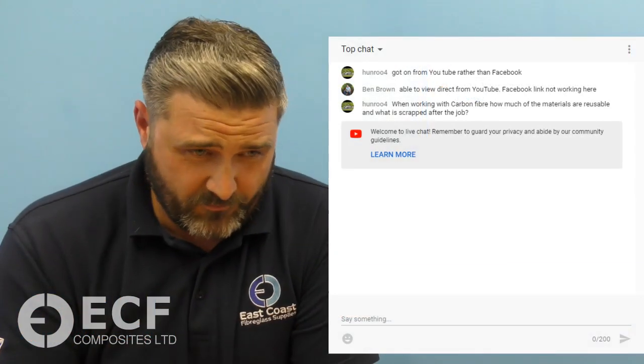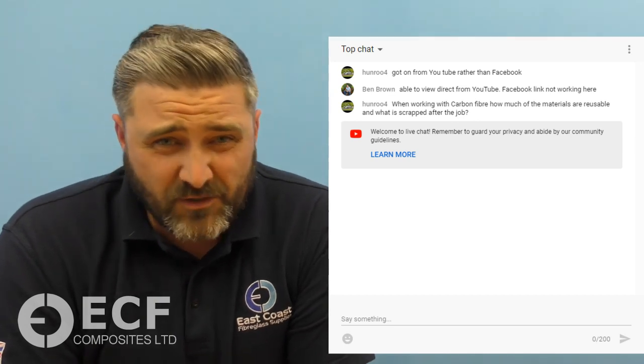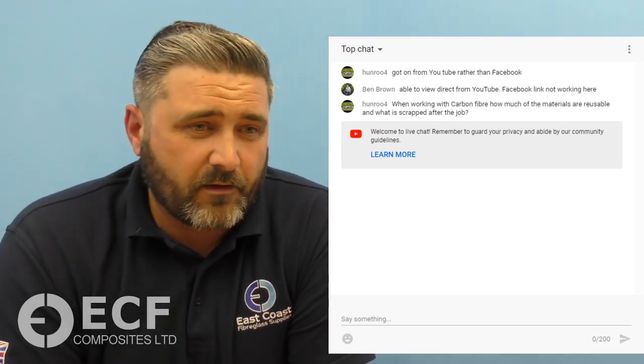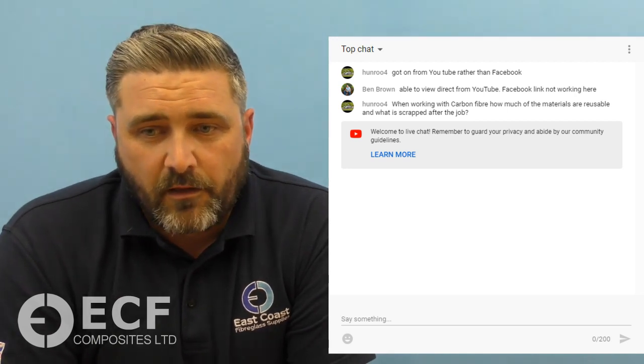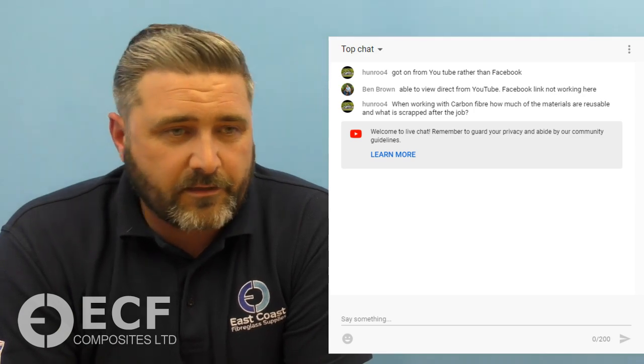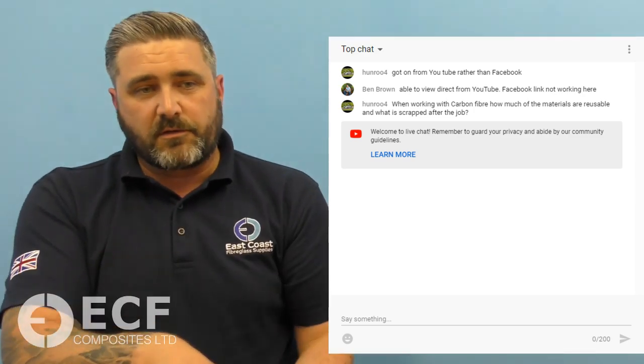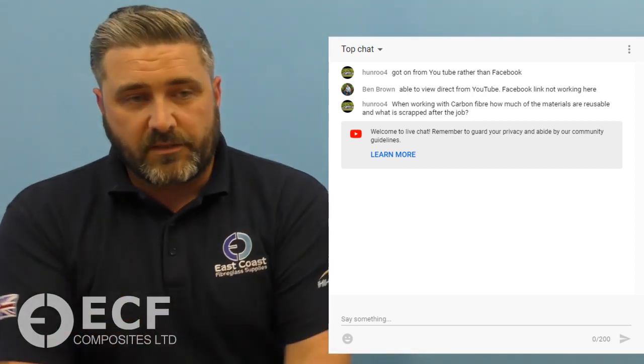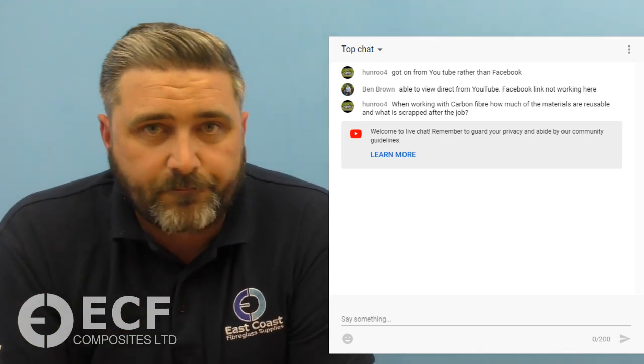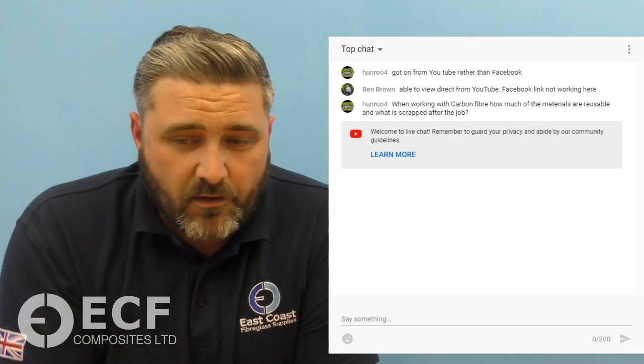Depends on the process you're using. If you are doing vacuum bagging processes, then you've got a lot of consumables that are going to be wasted. So you've got things like your low temperature sealant tape, the vac bag itself, release films. Unfortunately, they're not reusable, those. And if you did try to reuse them, you're risking damaging the part, having pinholes and leaks in the bags and things. So that's why high-end carbon parts are quite expensive. It's not just the materials, it's not just the process and the skill involved, but it's all the wastage and the consumables, the process and actually making them. So that's what normally bumps up the price of carbon fibre.